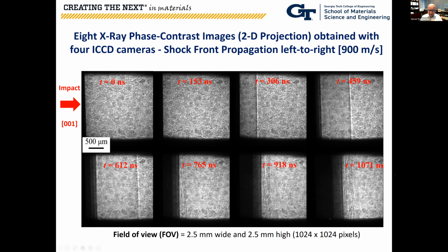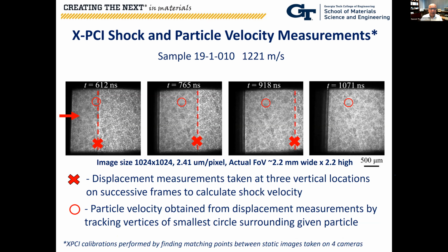So these are the images that we captured. Now, what do we do with these images? For example, in one of the images, we can clearly see the shock front. These are at 4 different time frames for the experiment performed at 1221 meters per second. You can see this front here.